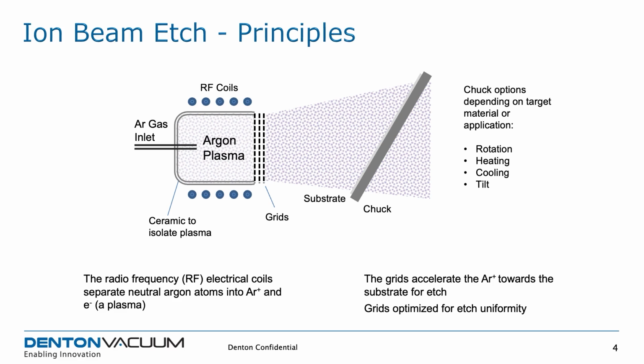So around the outside of that is the RF coils. Those keep the plasma lit. And on the front are the grids. So the grids pull the ions out of the plasma. Because you have these grids where you can set the voltages, you can actually independently control the ion energy, which is set by the grid voltage, and the ion current, which would be set by how much RF power you're dumping into the plasma.